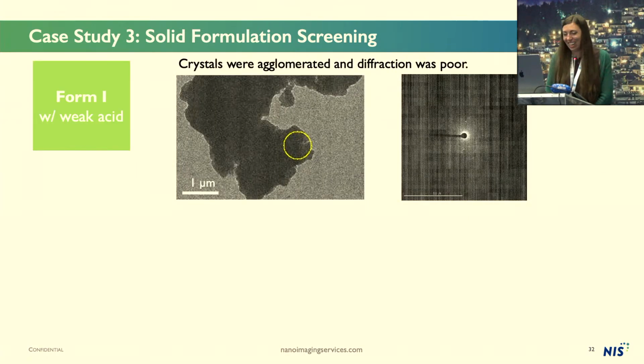So this was a very challenging one. They had good powder diffraction data showing that the bulk material was crystalline. When we put it in the microscope, we found just a lot of these large particles that appeared to maybe be agglomerates of much smaller crystals. This is showing almost no diffraction from this particle. We hunted around and we reached out to them.